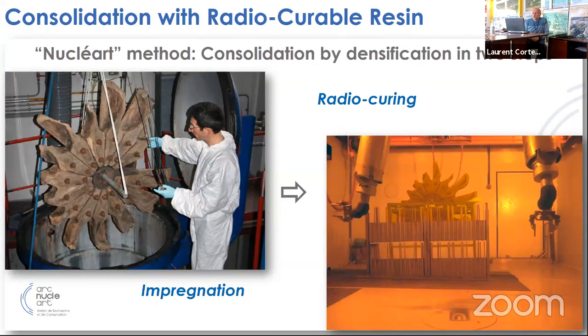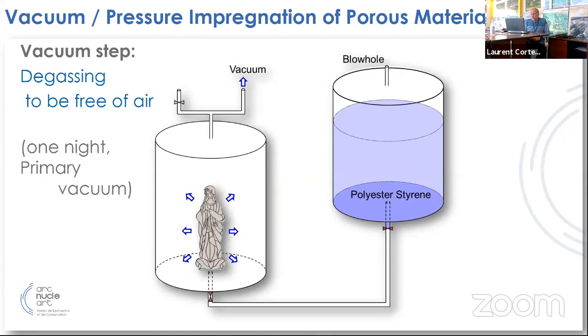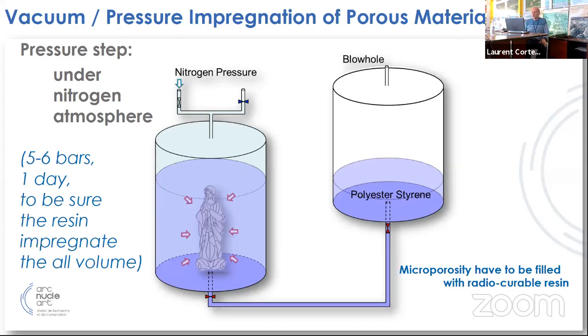The idea is to use radio-curable resin, gamma ray being just the tool that makes it harden inside the wood, in the bulk, after the artifact was impregnated by this resin. So we have first to impregnate the artifact. We will use vacuum. Firstly, we have to pump the air trapped in the porosity. And then we incorporate the resin with pressure in order to fill the microporosity. The resin will stay in the microporosity thanks to the capillarity force.